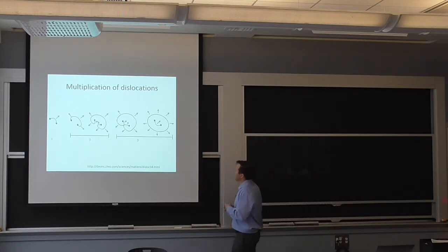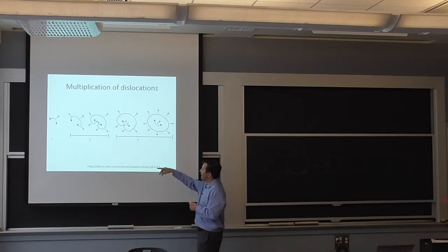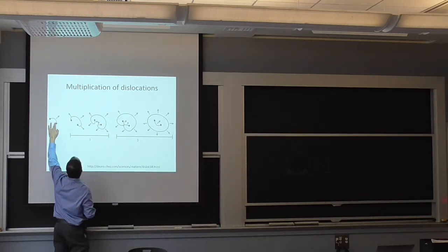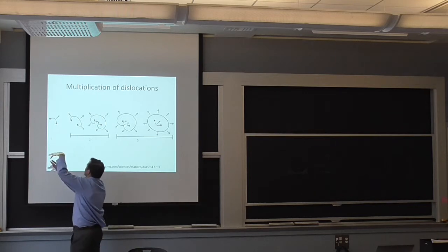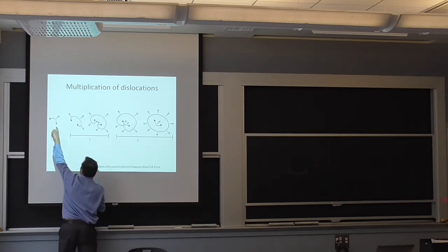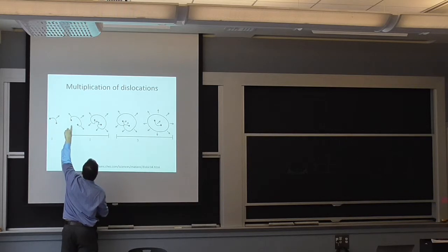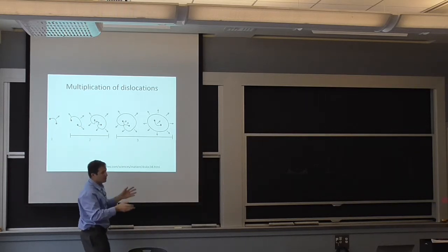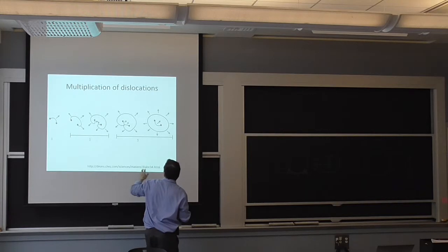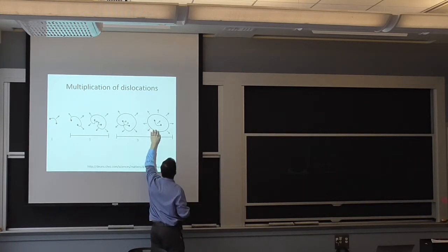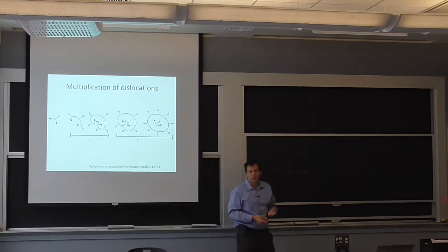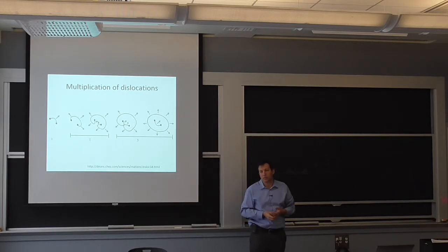The reason they multiply is you have these loops of dislocation, and normally they're not in the same plane — they go around in different planes in the microstructure and the grain. There will be a certain plane where it's a lot easier to move the dislocation. I have a loop that starts out of plane, and all I can see in this specific plane is one segment of it. The segment actually starts to move and expand, and when it's completely done I can recombine and now I have an extra dislocation. That's called dislocation multiplication.